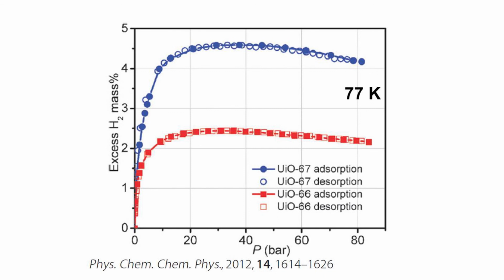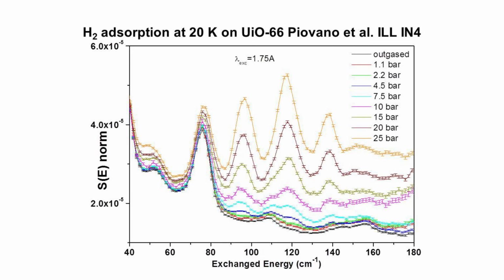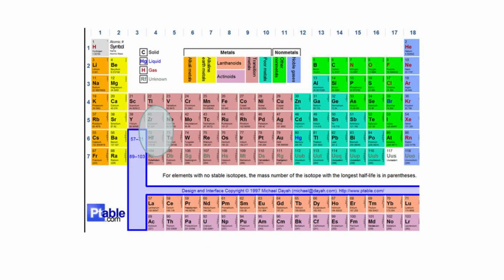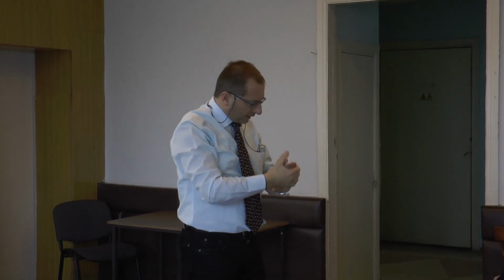In order to study the adsorption location of this hydrogen molecule, we ran inelastic neutron diffraction. This is inelastic neutron diffraction at ILL on the IN4 instrument. And then we are not happy about this. Remember the flexibility. I showed you the relevance of the flexibility in changing the ligand length. Now we use the flexibility of changing the inorganic cornerstones.